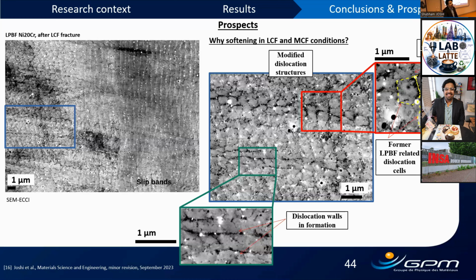Yes, certainly, because again we come back to residual stresses. If it's not heat treated, then we must have residual stresses in the as-built condition. So certainly it might influence dislocation behavior during tension. Different locations also have different behavior of residual stresses. So certainly it might influence, but it will only be understood when we compare the heat treatment analysis with the as-built. But yes, it might have an influence.